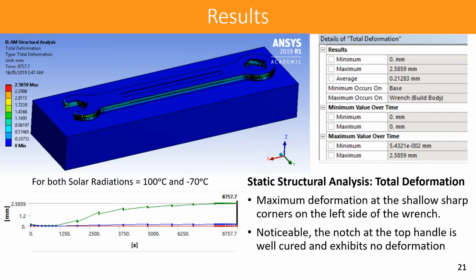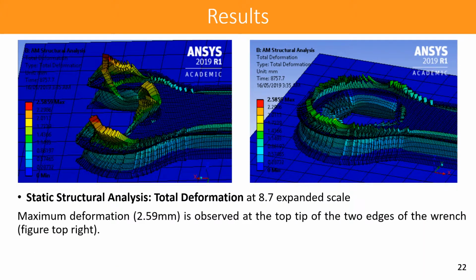For both studies, static structural yielded the same result. In the total deformation of the wrench, maximum deformation can be seen in the shallow, sharp corners on the left side of the wrench. Also, both sides of the wrench have higher deformation. Notably, the notch at the top handle is well cured and exhibits no deformation. This is an exaggerated view of the same. Maximum deformation of 2.59 millimeters is observed at the top tip of the two edges of the wrench.